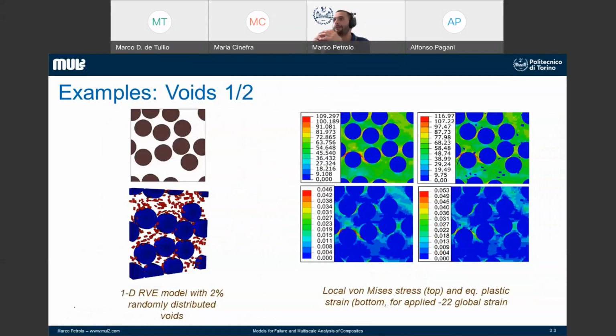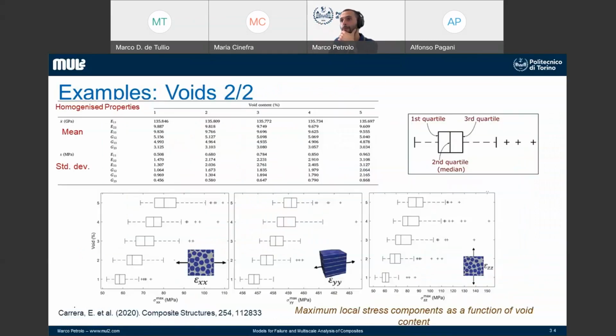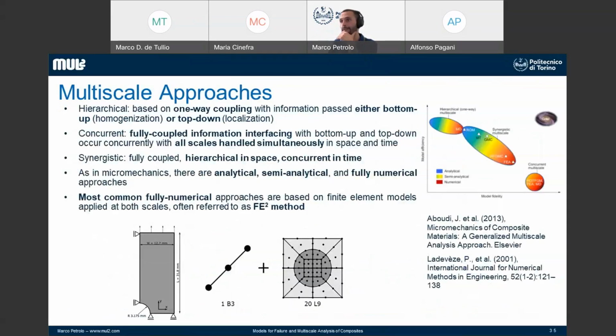For instance, in this case, we inserted voids inside the matrix. This is a typical defect you can get from manufacturing. And we then studied the effect of these defects on the stress field. So in these plots here, you can see how for different percentage of voids from 1% to 5%, you have different stress values. Different means that you can get a variation of also 20%. So higher the number of voids, higher the maximum stress field that you can get.